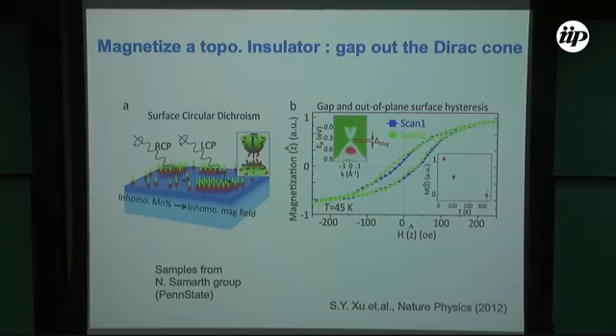There are two ways to create that. One is you dope magnetic impurities in the bulk of the topological insulator, or you deposit magnetic impurities on the surface. We have done both, and we found that even if the magnetic dopants are not homogeneous, from spectroscopic measurements we can tell that there is almost always time reversal symmetry breaking affecting the Dirac cone in momentum space, which is interesting. It's not immediately obvious why that should be so, because we're working in momentum space, k space. Why should we see a relatively nice gap when the magnetic field is not necessarily homogeneous? But this is an experimental fact that has been established.